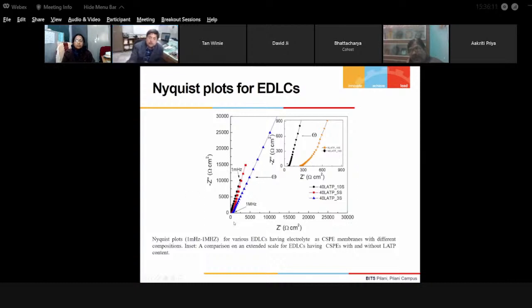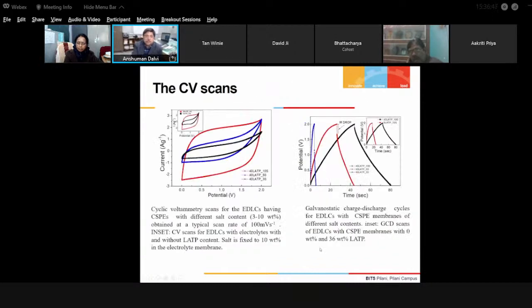Now there is no significant bulk impedance seen in this case, and that also signifies that indeed double layer capacitor formation is there even in the case of a solid interface. And then some kind of diffusive mechanism, Warburg nature, is also seen here. That also suggests a supercapacitor kind of behavior, which is normally shown by liquid and gel polymer based systems. So the nature of the Nyquist plots is similar to those of the other supercapacitors which are shown.